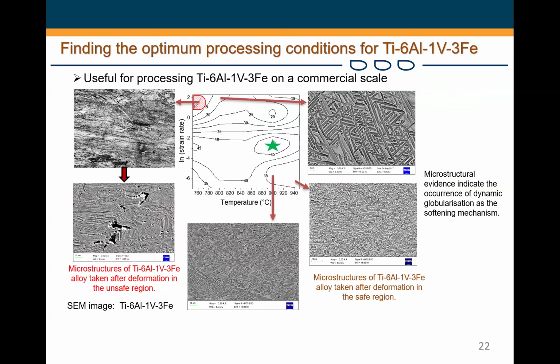So we came up with what is called a processing map, which was popularized by Prasad and co-workers around 2002. After getting our stress-strain data, we converted them to a processing map. And the processing map just gives you an idea of what's happening, basically. So if you process the alloy at this temperature and this deformation speed, which in the hot deformation space is called the strain rate, you would have a situation whereby you are introducing unwanted defects into the material, and we could confirm this using microstructure. You see, and this is not a microstructure you would like to have in your structural material, even for bone implant application.